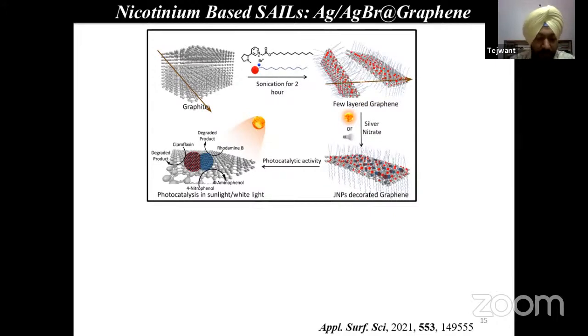Now the question arises, what is the stability of that exfoliated graphene? The exfoliated graphene was found to be very stable because the ionic liquid tends to adsorb at the surface of graphene layers. So now, as we have shown in the last example, we just needed silver nitrate and ionic liquid for the preparation of nanoparticles. In this case, we have the graphene that is extra.